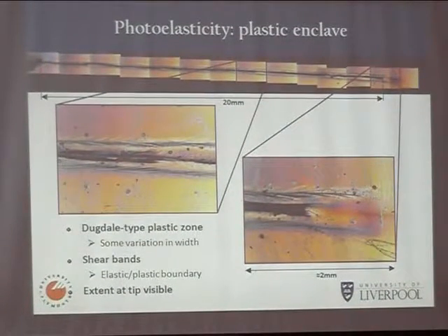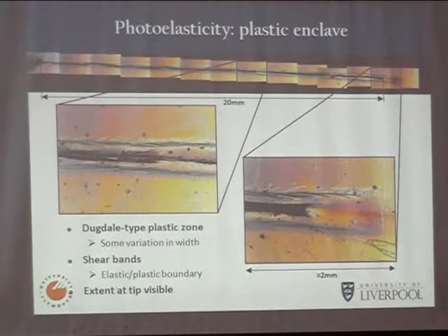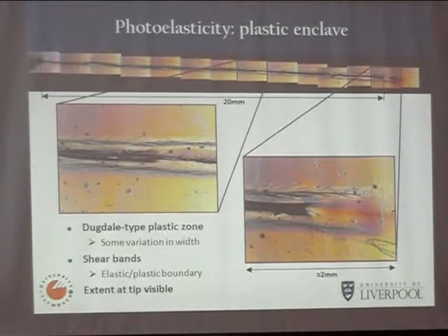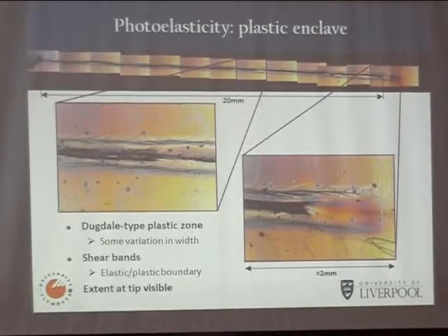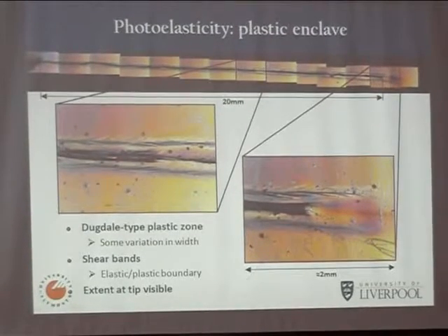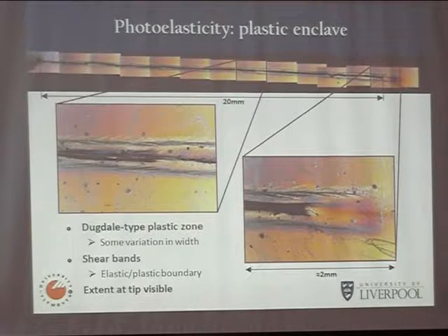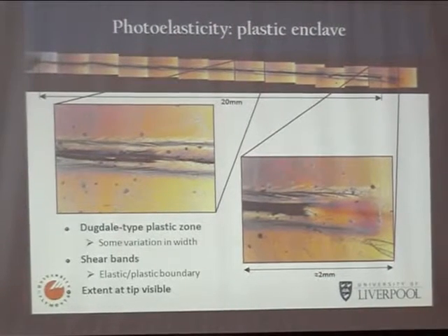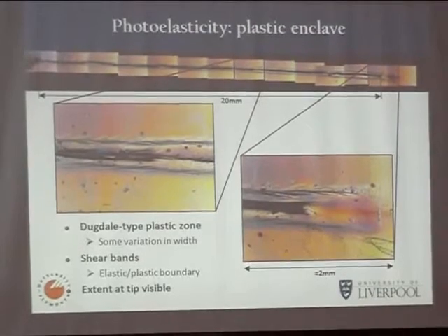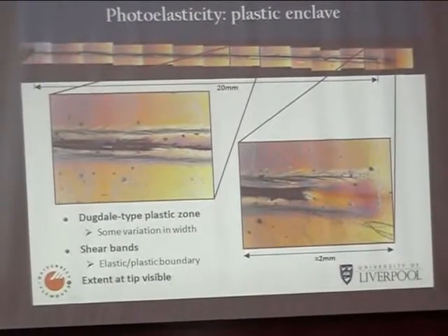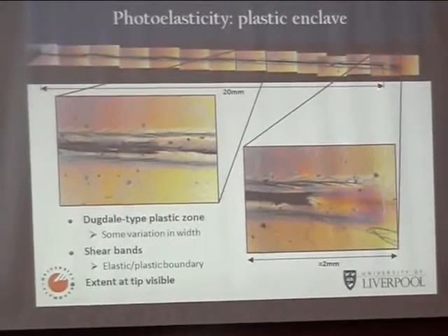Polycarbonate exhibits fatigue. The mechanism of crack growth is slightly different, and it occurs through a plastic zone being formed and then crazing occurring in the plastic zone, but otherwise it's analogous. And this is looking at a specimen following fatigue crack growth in an optical microscope. So this is unloaded, so this is a residual field. And this is a mosaic of the crack, 20 millimeters of crack growth.